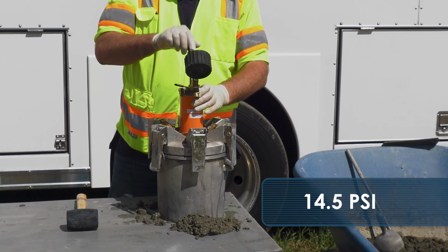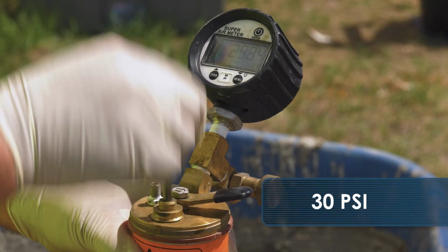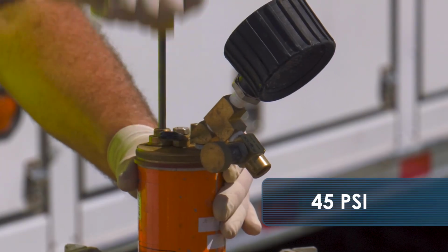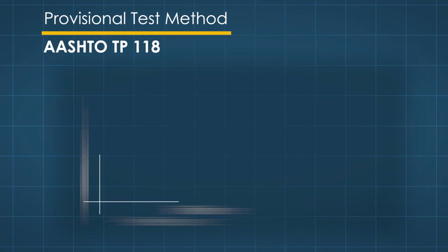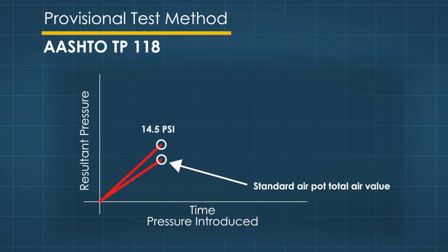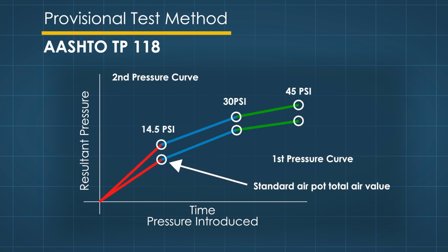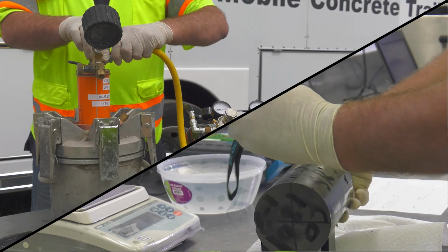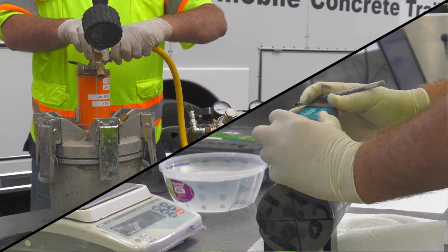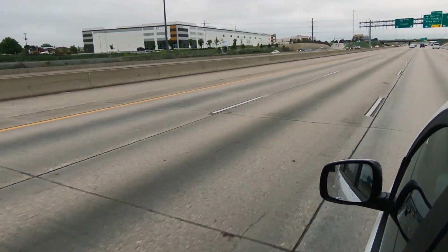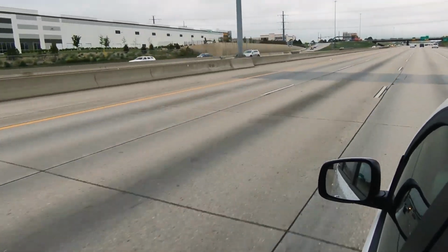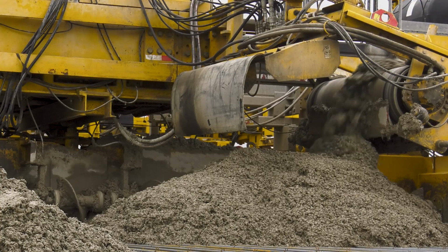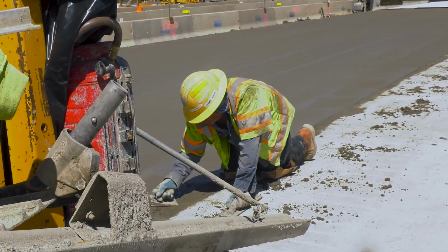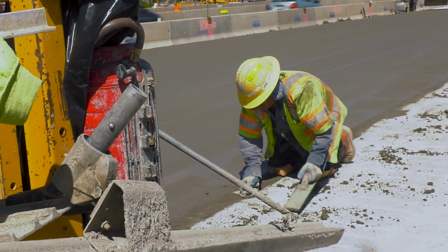The testing procedure calls for running the test several times without releasing the pressure from the bottom bowl and provides data under increasing air pressure. If you have tiny bubbles evenly spaced throughout the concrete, the first line and the second line will be very close to each other. If they are too far apart, then that particular concrete is not good from a freeze-thaw standpoint. The super air meter and surface resistivity test measure durability in a much shorter time frame based on performance indicators to predict how durable concrete is or how long the concrete could potentially last.